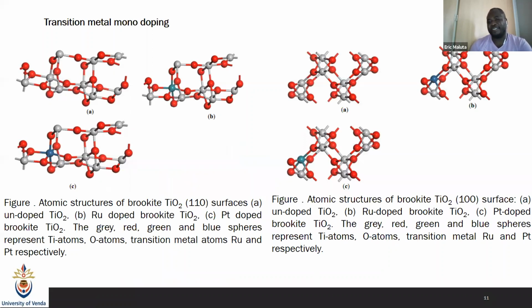And what we did was to look at transition metal doping. We have doped with different transition metals, but here I'm just showing the doping by ruthenium and doping by platinum for the different Brookite surfaces. We have the 1,1,0 surface on my left, and the 1,0,0 surface on my right. And then we can dope with different things: in B here, we dope with ruthenium, and in C, we dope with platinum.